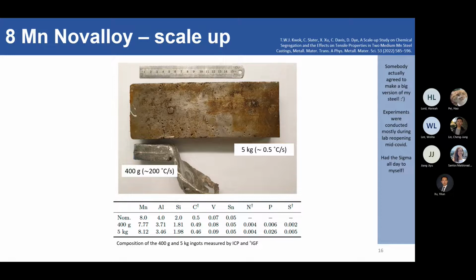It sounds very common sense, right? But in DP steels with only 2 to 3% manganese, you still get manganese banding and segregation. So this is an important study to conduct, right? This big ingot here has been solidified very slowly at 0.5 degrees per second, and that's representative of what you see in the industrial continuous casting process.